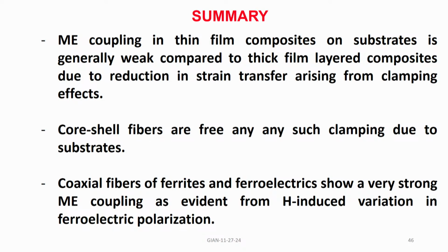The traditional methods for exploring the nature of the magnetoelectric interactions in all of these systems are either ferromagnetic resonance under an electric field, or magnetization versus H under electric field. These two are for the converse magnetoelectric effect. For the direct magnetoelectric effect, people used measuring P versus E under H, or the low frequency magnetoelectric voltage coefficients.